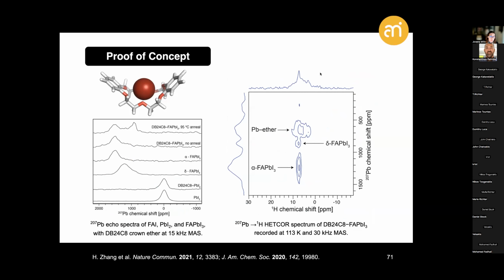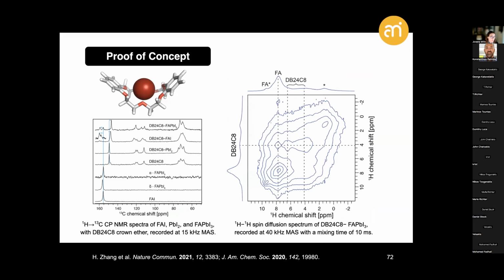binding capacity. Similarly, this was done with formamidinium cations by using carbon NMR spectroscopy, as well as, in this case, proton-to-proton spin diffusion experiments, correlating again the environments of the crown ether with those of the formamidinium cations, suggesting their presence in the nanoscale proximity and confirming their binding capacity, that was also complemented by density functional theory calculations.